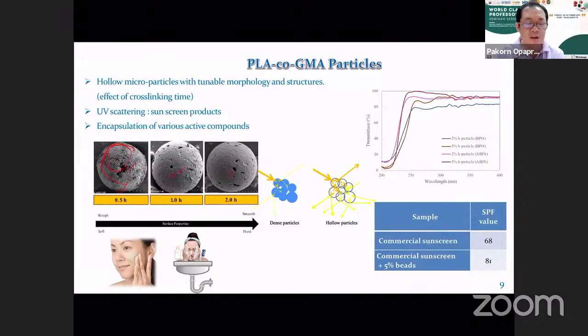But when we increase the degree of cross-linking, this will inhibit the chain movement or the crystallization of the chain, and this makes the morphology of the particle become smoother. So then we also know that if the particles have a hollow structure here, they can scatter light very well, especially in the UV region. So this can be applied as nanoparticles for cosmetic, especially sunscreen applications.